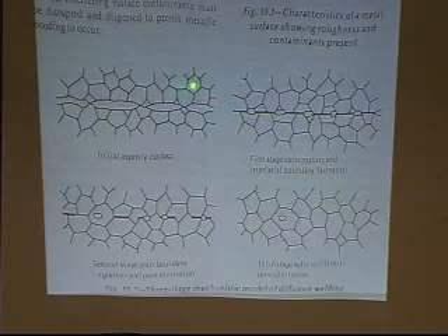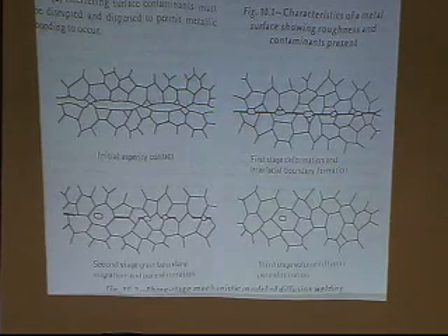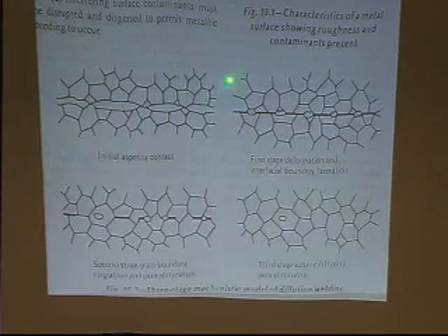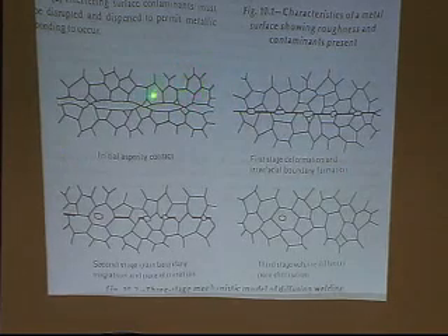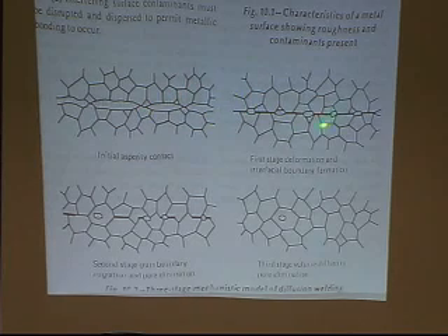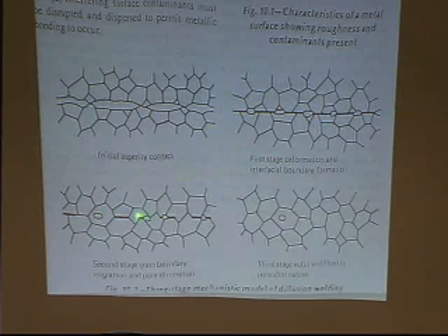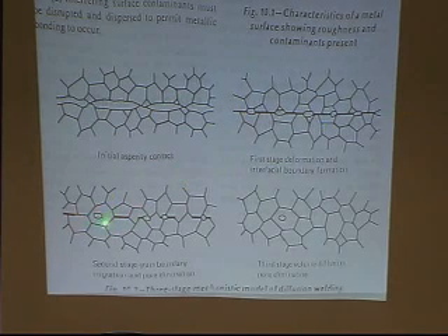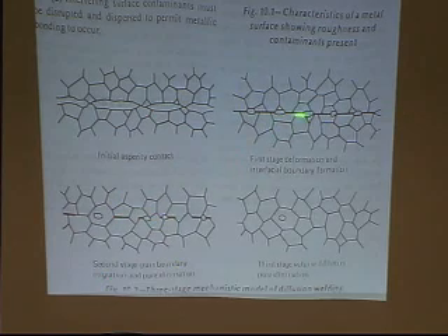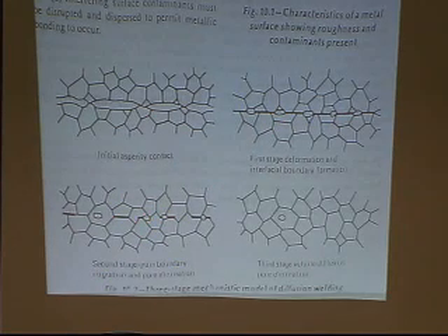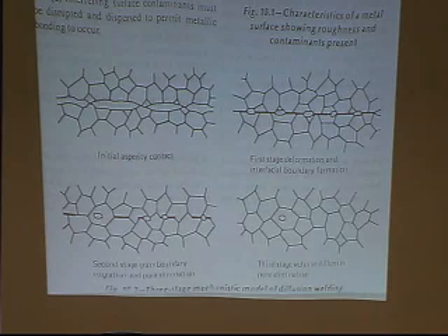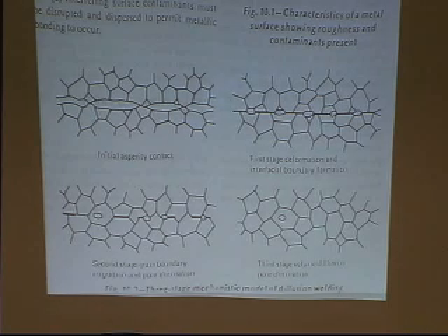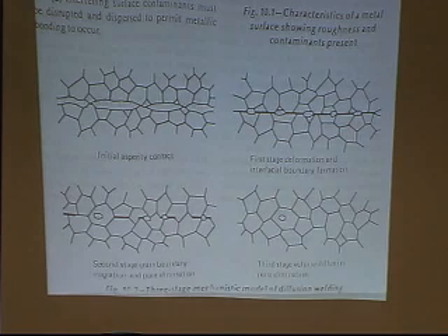So you had these grain boundaries here. Everybody know what grain boundaries are? You have different crystals of the metal. Okay, they all have slightly different orientation, and in between those you have what we call grain boundaries. So each one of these is a little single crystal grain, and you pack them all together, and where they come together, it's called a grain boundary. Okay, so this is the first stage. In the second stage, you actually have these grains start to grow: grain boundary migration and pore elimination. Some of the pores, essentially the vacancies, a pore can just be considered an inclusion consisting of lattice vacancies. So the vacancies can diffuse away at the grain boundaries. The grain boundaries actually act as sinks. If I have a vacancy and it goes into a grain boundary, it just causes the grain boundaries to collapse together a little bit, and they get smaller.